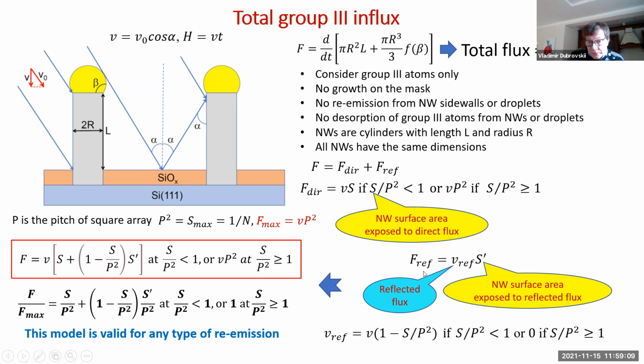So then, for the reflected flux, it equals V reflected times the nanowire surface area exposed to the reflected flux. And from the total balance of gallium, we can write that V reflected equals V times 1 minus S over P squared, provided that S over P squared is smaller than unity, or 0 when S exceeds the P squared, simply because in this case all mask is shadowed by the nanowires. So from these considerations, we have this, of course, simplified expression. So F equals V times S plus 1 minus S over P squared S prime. Or for the flux normalized to its maximum value, we have this.